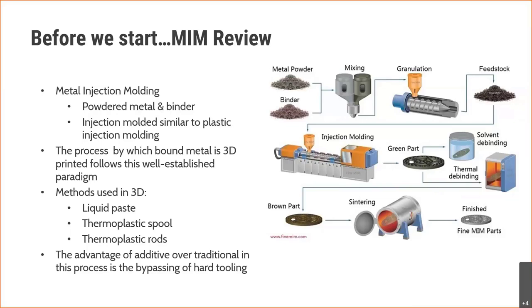You have to go through what's called a debinding process, which means that you have to remove the plastic or the binder material that's holding the metal together so that the part retains its shape, which then in turn gives you a brown part, which you then sinter. The sintering process, which I'll talk about briefly in the next slide, is applying heat just below the melt temperature of the metal, enough so that you bond the adjacent small spherical powder particles together to form a solid metal part.